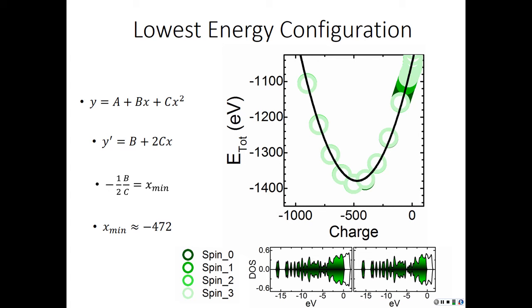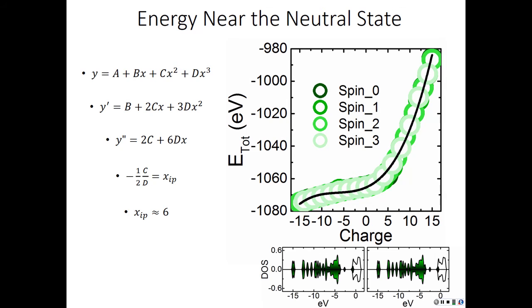Yeah. Okay. So what we wanted to do first was just explore the different oxidation states and charges of the system to see if we can find a lowest energy. When we did that, we found that the lowest energy was at a charge of about negative 500, which is extremely low. So we decided to explore different areas, and looked at the charges around the neutral state. Here we see a deviation from the parabolic function we saw earlier to a cubic function, with an inflection point around 6. This inflection point doesn't give us a whole lot. I looked at the density of states around it, and it seems to be similar.